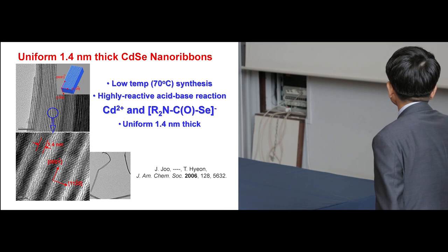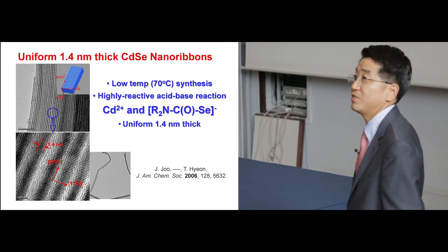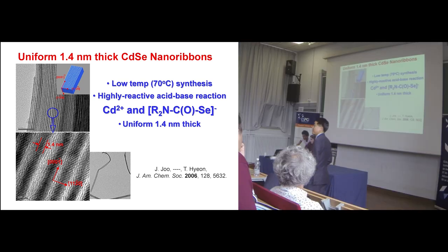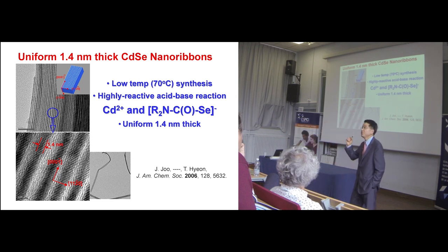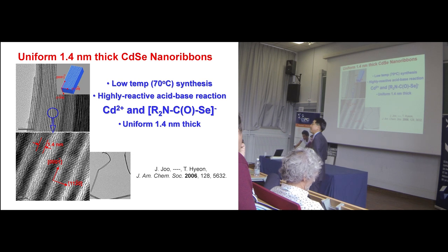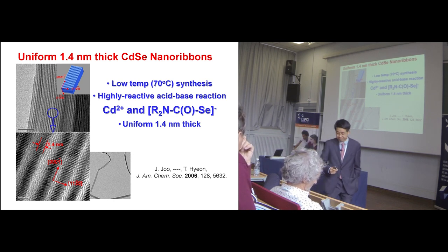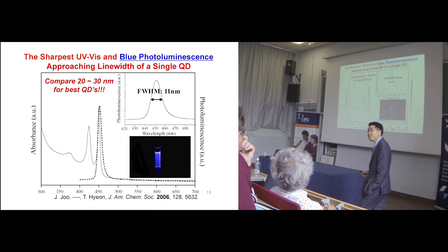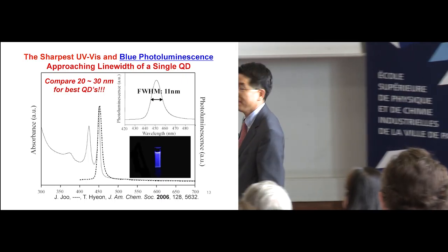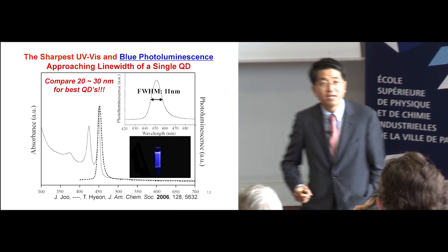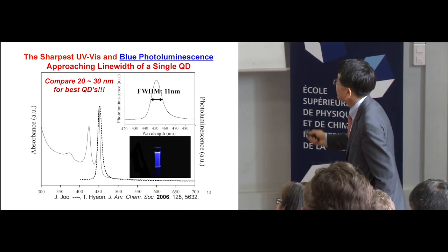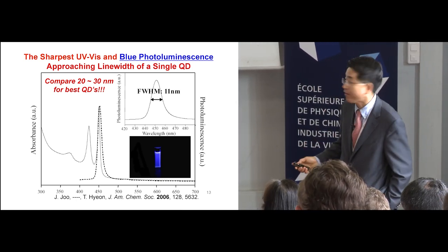And if you look at thickness, that's 1.4 nanometer, which is absolutely quantum confined. So this is the first demonstration that the 2D, two-dimensional, freestanding, colloidal quantum nanostructure can be generated. And then even more exciting is the fluorescence, okay? If you look at the photoluminescence, in particular, it gives a blue light, okay?